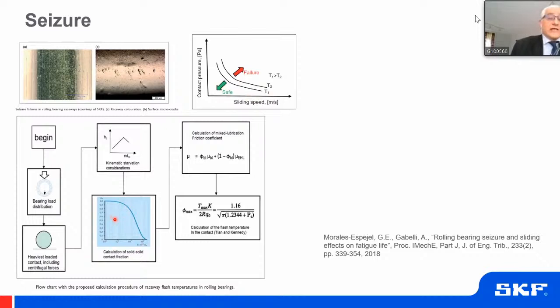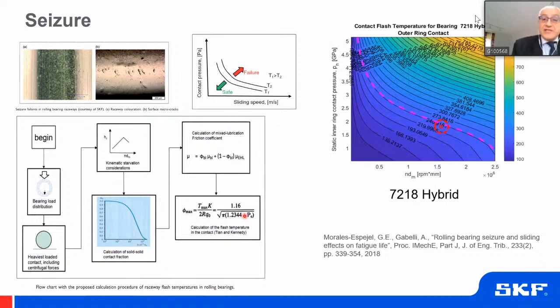From that, we calculate the percentage of metal to metal contact that we may have in a mixed lubrication model, an average friction coefficient, or you can use the local friction coefficient if you have a numerical scheme. And then we can calculate the local temperatures on the surface. And if you draw these temperatures versus speed and pressure, we get these isothermals, which is basically the transition diagram. The only thing you need to do is to place an experiment to know which of these isothermals is the one that you are looking for as the transition diagram of your problem.